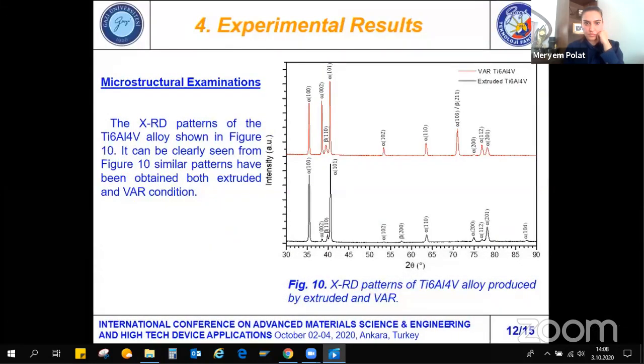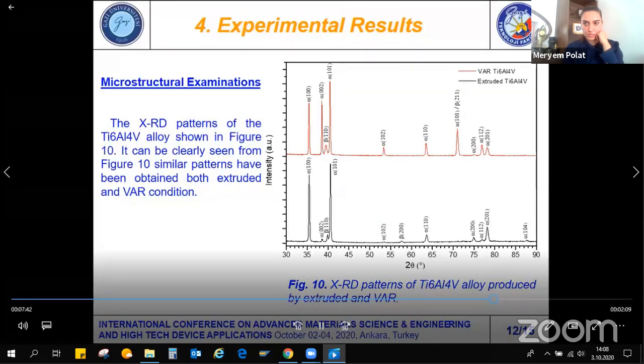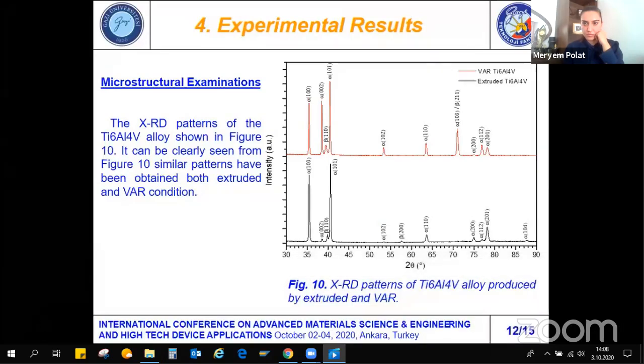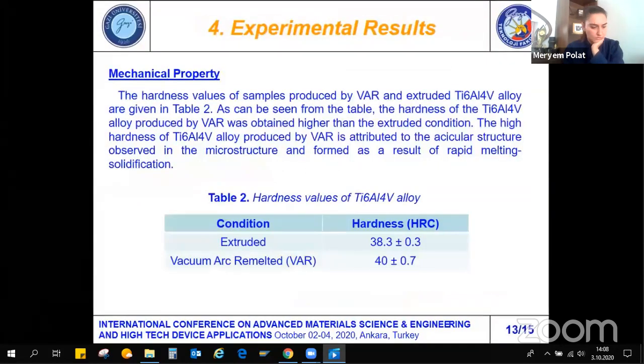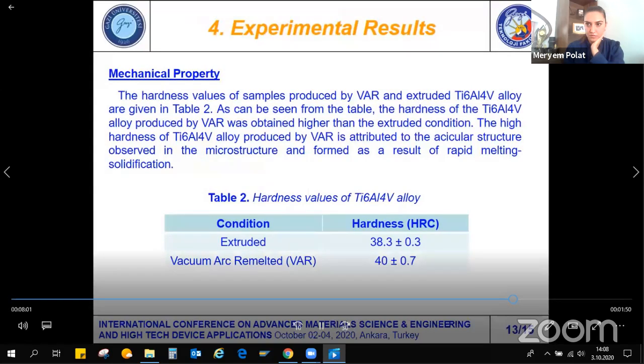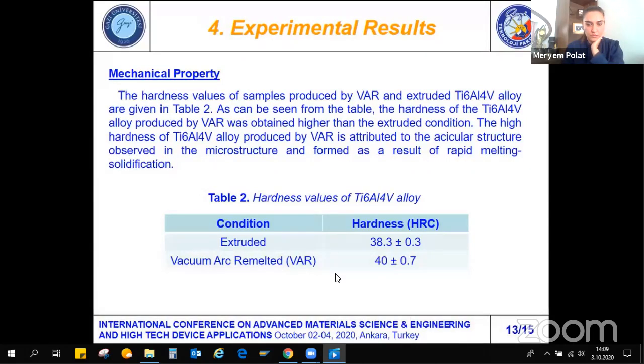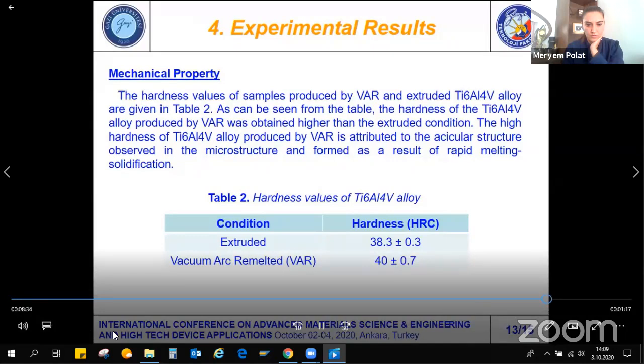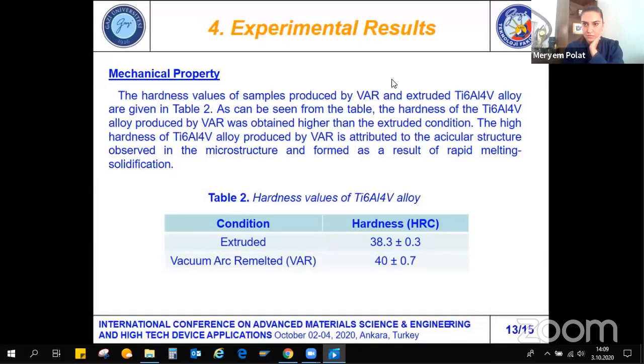The XRD patterns of the titanium 6 aluminum 4 vanadium alloy are shown in figure 10. It can be clearly seen from figure 10 that similar patterns have been obtained in both extruded and vacuum arc remelted conditions. The hardness values of samples produced by vacuum arc remelting and extruded titanium 6 aluminum 4 vanadium alloy are given in table 2. As can be seen from the table, the hardness of the alloy produced by vacuum arc remelting was higher than the extruded condition. The high hardness is attributed to the acicular structure observed in the microstructure and formed as a result of rapid melting and solidification. The extruded hardness is 38.3 and the vacuum arc remelted hardness is 40 Rockwell C.